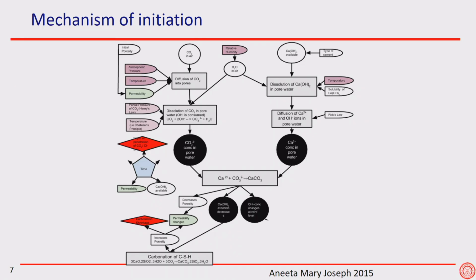I'm only showing you half of the flow chart. I'm not even showing you the other half. It's a complex process. This is what I realized. I used to think this is something very simple. CO2 goes in, reacts, and that's it. And then we realized there are so many steps to carbonation. There's diffusion of carbon dioxide, there is the dissolution, there is the reaction, there's diffusion of lots of other things, including moisture, there is precipitation of carbonates, lots of things can happen.